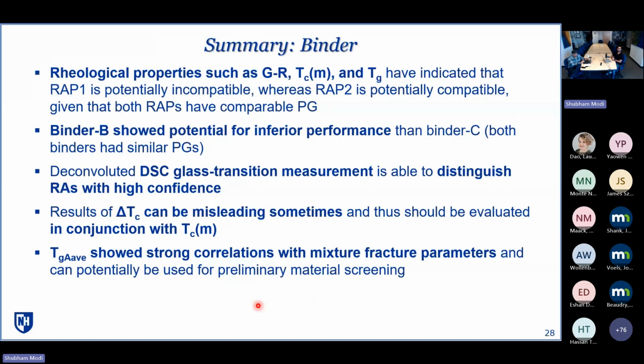And coming to the summary from the binder perspective, rheological properties such as Glover-Rowe, TCM, and TG are able to differentiate or characterize the RAP sources, along with the binder sources. However, the deconvoluted DSC measurements were better in distinguishing the RA effect with higher confidence than the rheological parameters. And as discussed, the delta TC should be evaluated in conjunction with TCM, as most of the binders nowadays are PMA controlled binders.